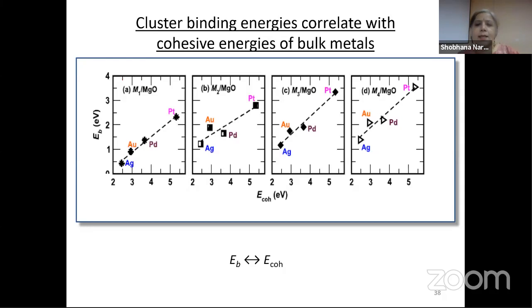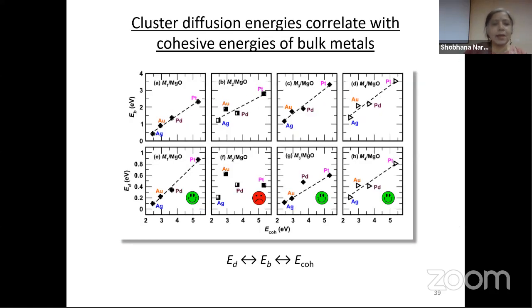Now, the cluster binding energies correlate with the cohesive energies of the bulk metals. This makes sense because you have these interatomic bonds, and when you break some of them to form the cluster, then they want to compensate for that, and so they form bonds of similar strength with the substrate. So this is shown here. You see that in all cases that correlation holds. So again, if the cluster binding energy correlates with the cohesive energy, and if the diffusion energy correlates with the cluster binding energy, then the diffusion barrier will correlate with the cohesive energy, except in the case of the dimer for the reasons I have already discussed.